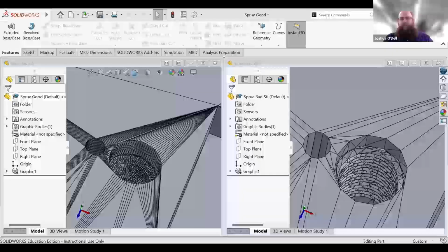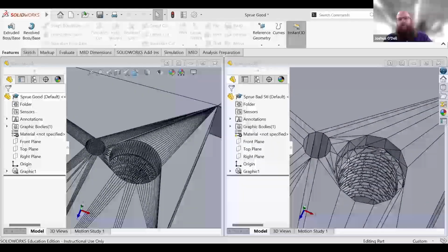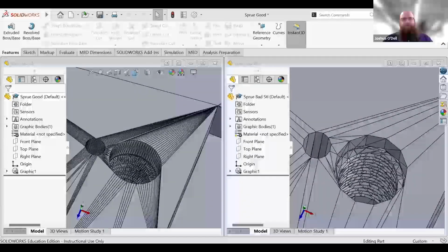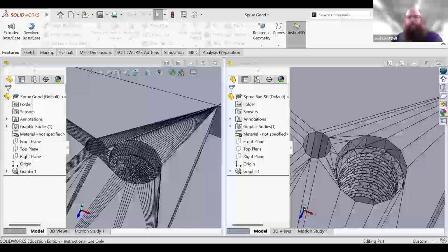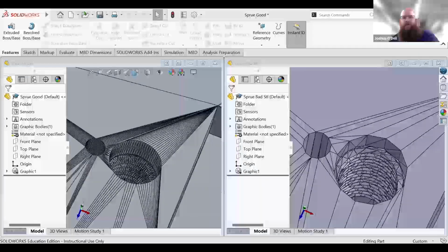In terms of surface finish and shell adherence, hey AJ, did you dip it in a wash before you printed with it too? Just your typical wax wash? Oh, okay. The wax printer patterns we use as well, you guys use Citru Etch. The 3D printed wax patterns, we haven't needed to etch them first. But we're usually printing pretty small things on that printer. And it usually doesn't have much issue sticking because when you clean off the parts in that IPA, it roughs up the surface a little bit already. So it wasn't as much of a problem for the slurry to attach.